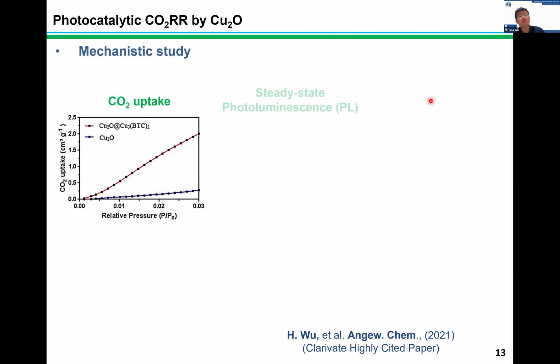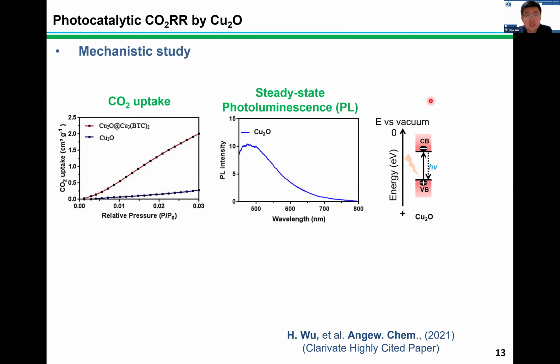To prove that, we first did the steady-state photoluminescence studies on our sample. For the bare cuprous oxide, it shows an intrinsic emission signal centered around 500 nanometers. Upon the deposition of copper MOFs as the shell, in addition to the intrinsic emission signal of cuprous oxide, we create a new emission signal centered around 630 nanometers. So we're curious about where the new signal comes from.